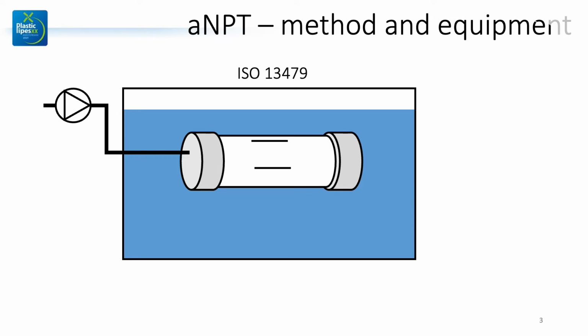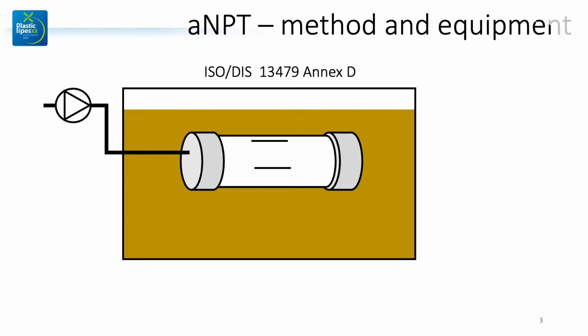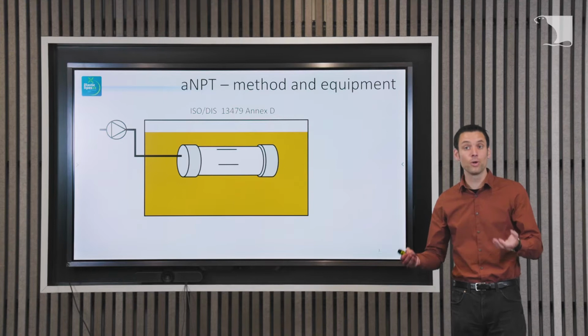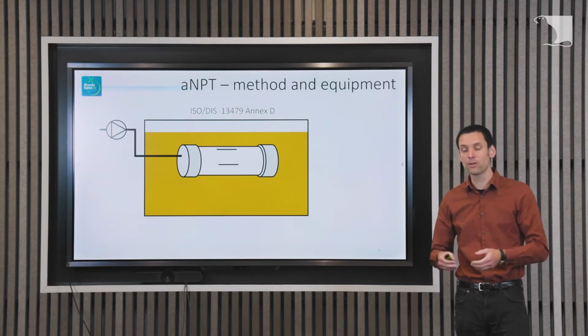The only thing is that for polyethylene pipe with raised resistance to slow crack growth, it takes just too long to let it fail within a reasonable time. So what can we do to accelerate it? Well, we put in a detergent. So now the pipe is not submerged in water, but it's submerged in a detergent solution. And that will accelerate the test spectacularly.